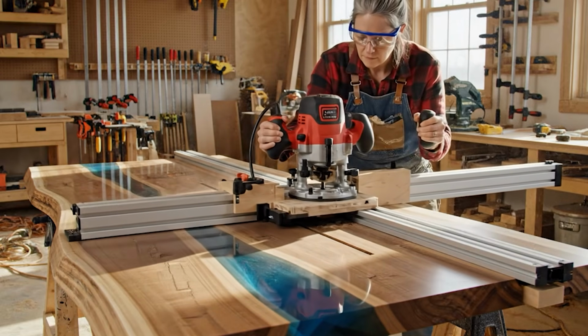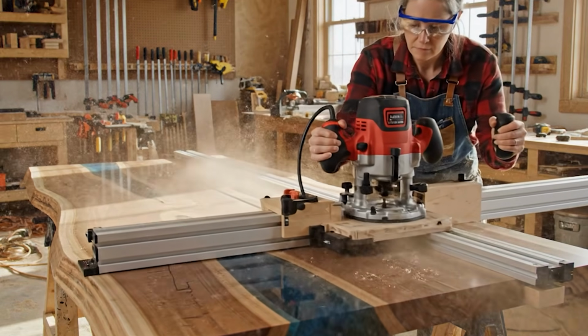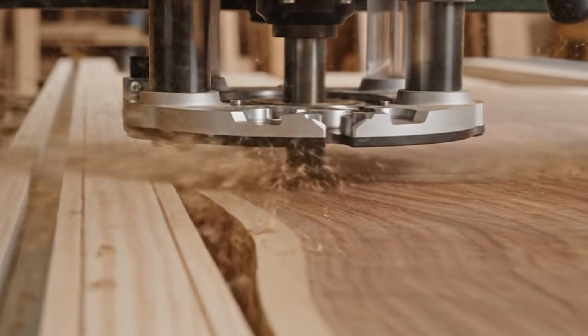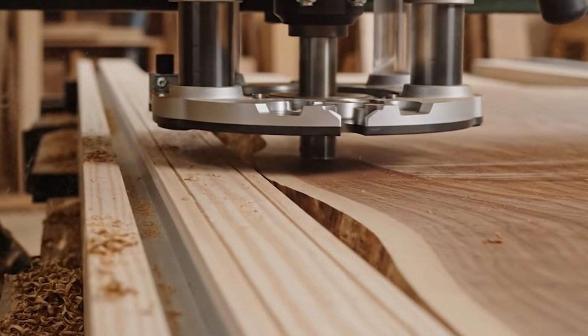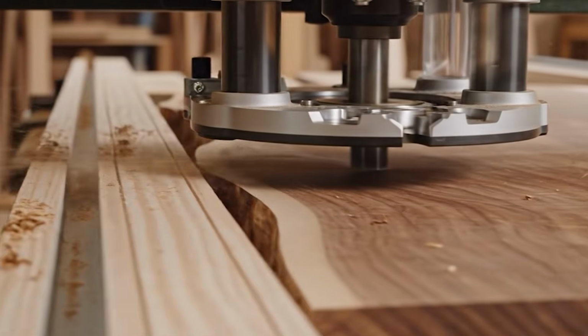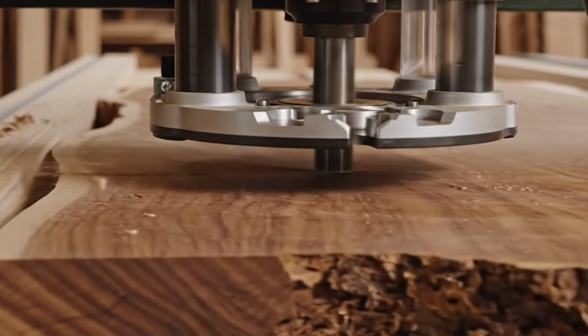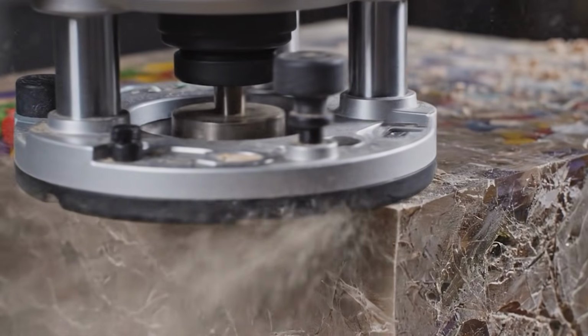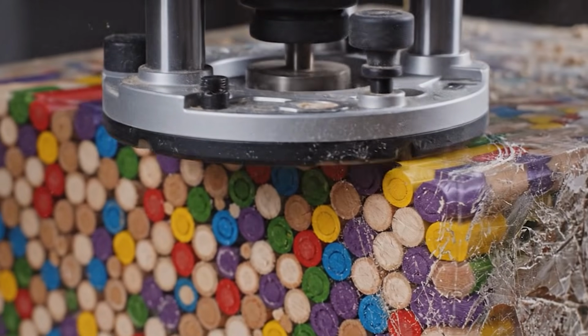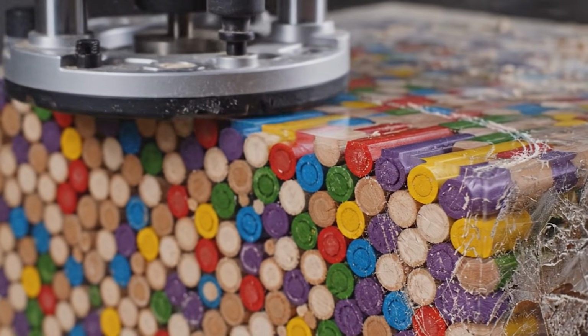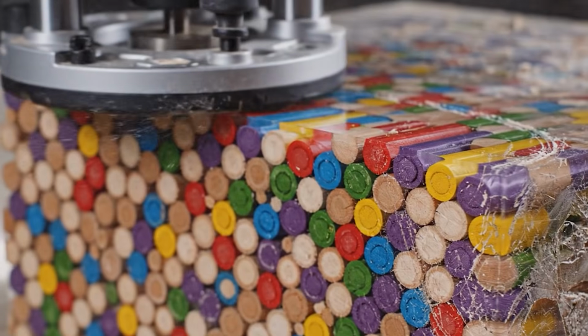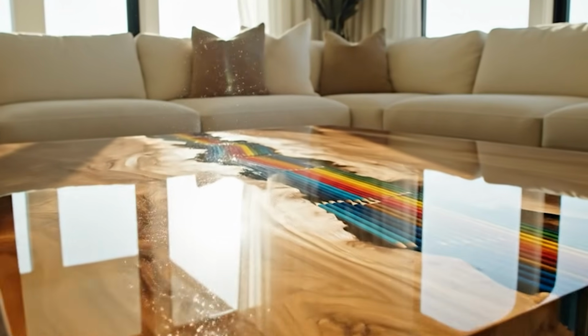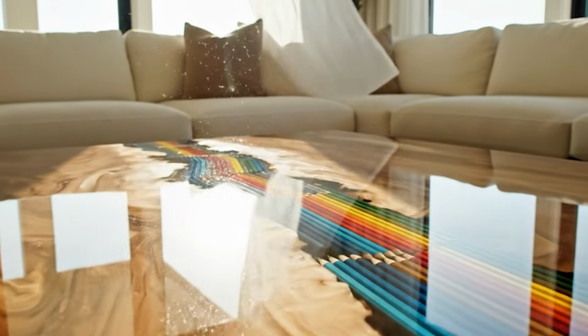Build a simple sled from 2 straight boards that span across the slab and run a router with a 2-inch surfacing bit back and forth, taking off about a 32nd of an inch per pass. This is the moment where the magic happens. As you flatten through the top of those pencil segments, the cross-sections of every single colored core are revealed in perfect little circles embedded in crystal-clear resin. It's one of the most rewarding reveals in all of woodworking.